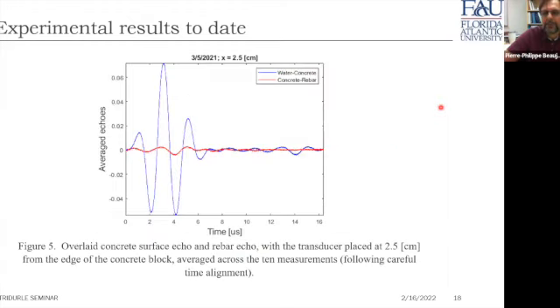Now, figure 5 shows an example of the echo measured at the water concrete interface in blue, and lined up on top of this echo, we put the concrete rebar echo measured by the transducer. So that's an overlay plot, okay? And that was for when the transducer was placed 2.5 centimeters from the edge of the concrete block, and this result was averaged over 10 measurements.